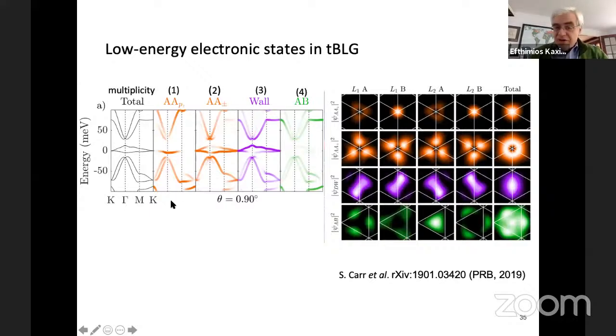So what we can do with our theory is understand the nature of these electronic states. So these are the bands again that I was showing you, the two bands near the Fermi level, which are pretty flat. So this is at an angle of 0.9 degrees. You see the flat bands, and now we can take these flat bands and project out of these bands the different components of the electronic behavior. So this plot here shows you the different components of the electronic behavior. There are actually four different columns and a final one at the end, fifth. The first column is layer one, lattice A, then layer one, lattice B, layer two, lattice A, and layer two, lattice B.